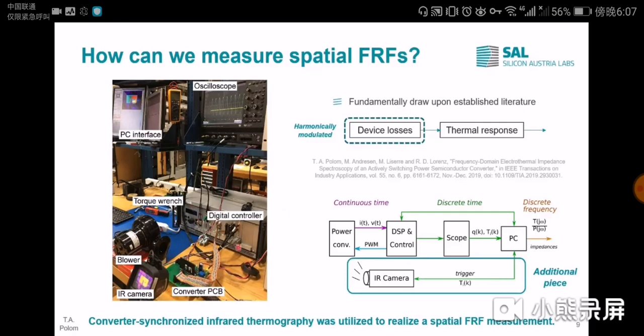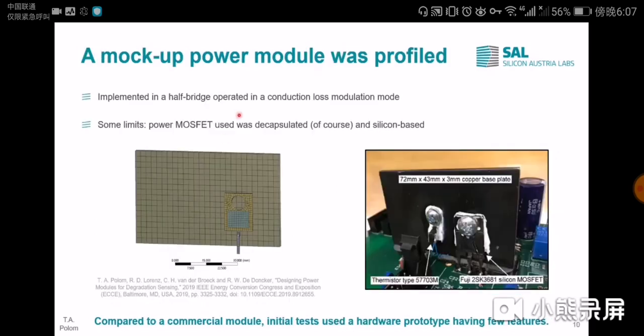What I want to focus on the most is that we have a converter PCB, so the half bridge was actually oriented in this vertical way in which the base plate of the mock-up power module was oriented normal to the infrared thermal camera. The mock-up power module is displayed here. It was implemented in a half bridge, operated in a conduction loss modulation mode, as I mentioned, and it's a single active Fuji silicon MOSFET bonded to a base plate with a screw-in thermal interface material. The thermistor was not used in this study, but rather in other studies.